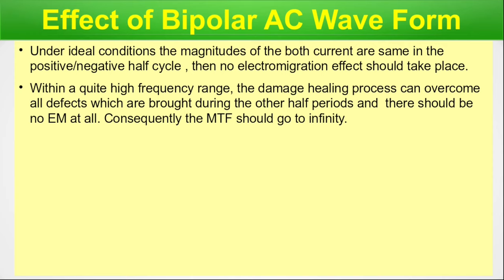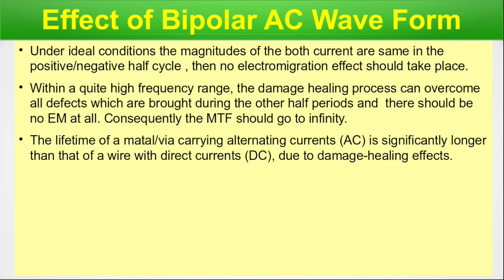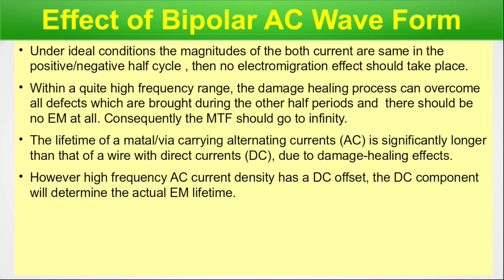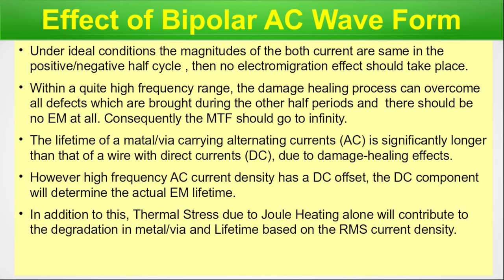So if you can recall the slide in the last episode where I have shown the infographics about the shifting of the MTF point, that point here in this particular bullet, as per the condition, will move towards infinity. The lifetime of a metal or via carrying alternating current AC is significantly longer than the wire with direct current DC due to the damage healing properties of the AC waveform that so far we have discussed. However, in high frequency AC, if the current density has a DC offset, the DC component will determine the actual EM lifetime. In addition to this, the thermal stress due to the Joule heating alone will contribute to the degradation in the metal or via lifetime based on the RMS current density.